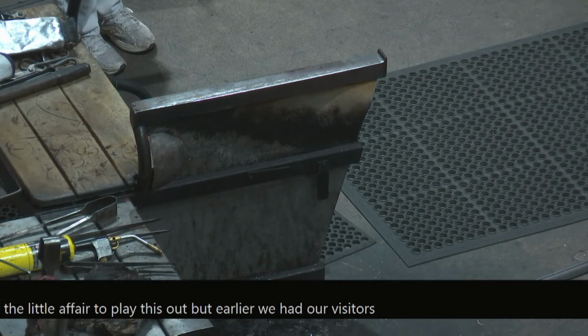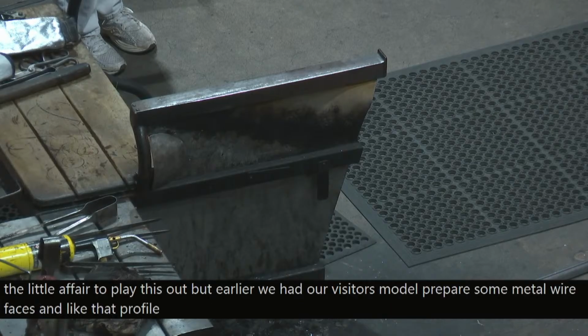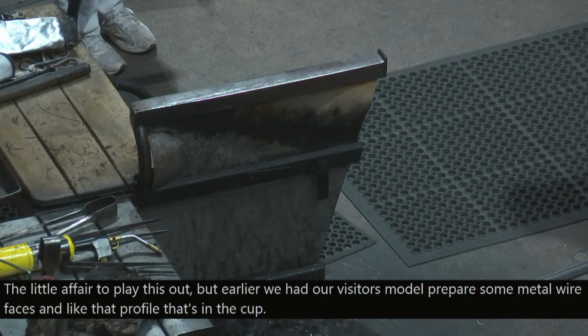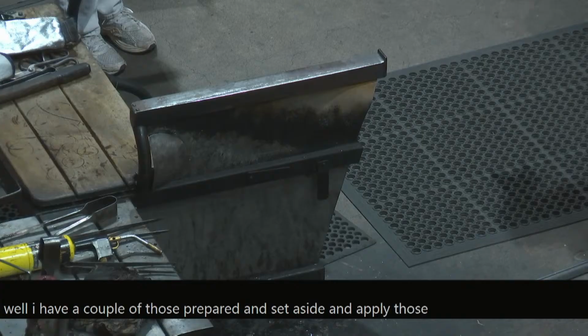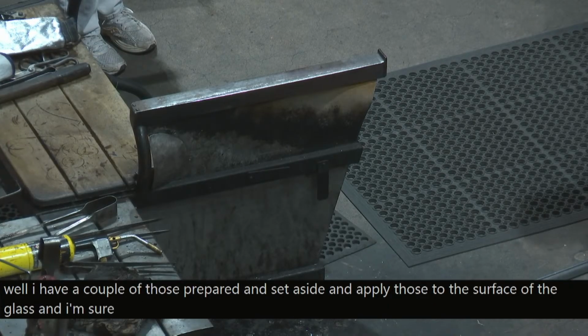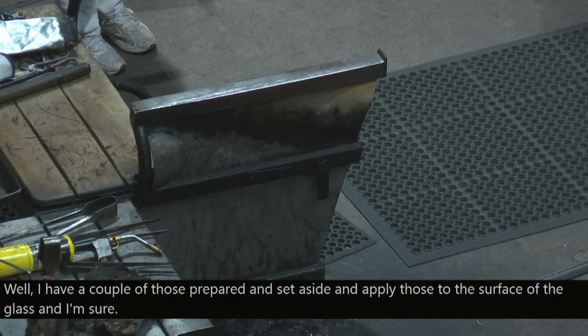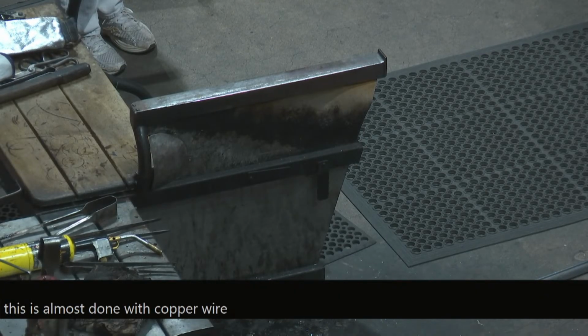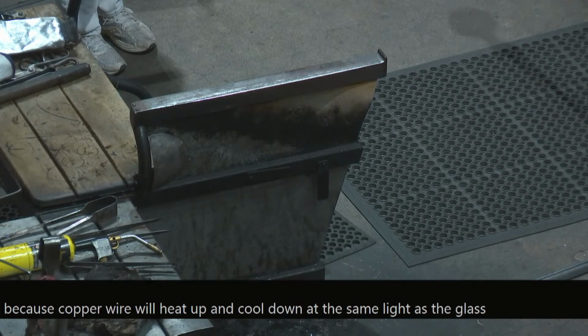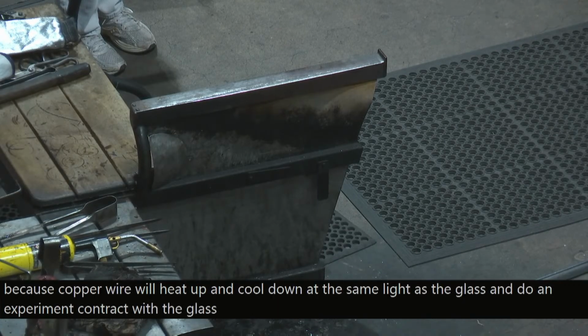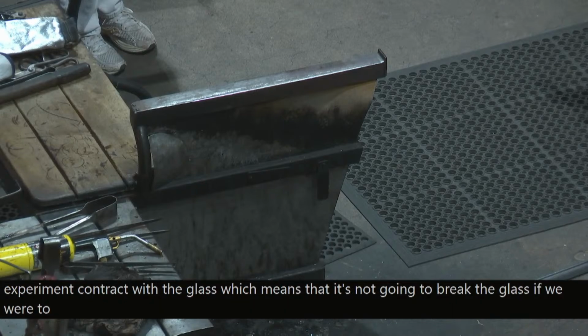And I don't know if I already pointed this out, but earlier we had our visiting artist Lonnie prepare some metal wire faces, you know, like that profile that's in the cup. We have a couple of those prepared and set aside, and we'll apply those to the surface of the glass eventually. And very importantly, this is always done with copper wire, because copper wire will heat up and cool down at the same rate as the glass and kind of expand and contract with the glass, which means that it's not going to break the glass. If we were to try to do this with steel, then it would just crack the glass surrounding it.